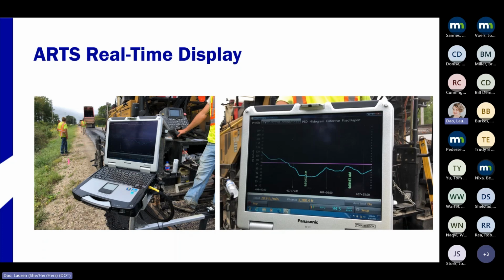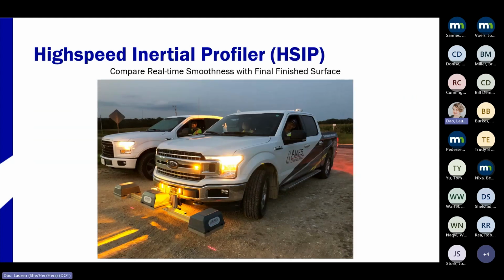You can see a red line on the image on the right, and that's your threshold for roughness. If you exceed that, you might want to tweak the paver operation a little bit to bring it down. After the paver operation, after the finishing roll is done and the asphalt is cooled down, we also profile the exact same location with a high-speed inertial profiler, just to compare the results of how it was behind the paver screed and how it turns out after the compaction is done.